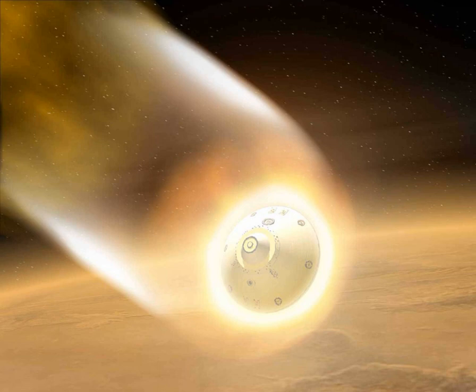SLA-561V begins significant ablation at a heat flux of approximately 110 W per square centimeter, but will fail for heat fluxes greater than 300 W per square centimeter. The MSL aeroshell TPS is currently designed to withstand a peak heat flux of 234 W per square centimeter. The peak heat flux experienced by the Viking 1 aeroshell which landed on Mars was 21 W per square centimeter.